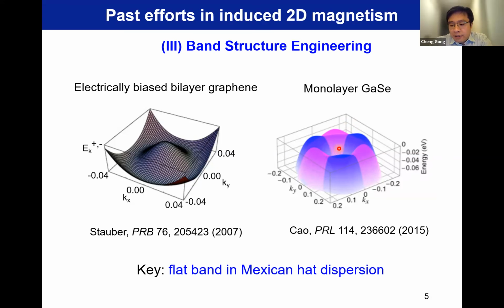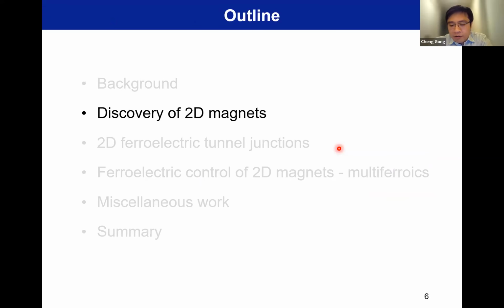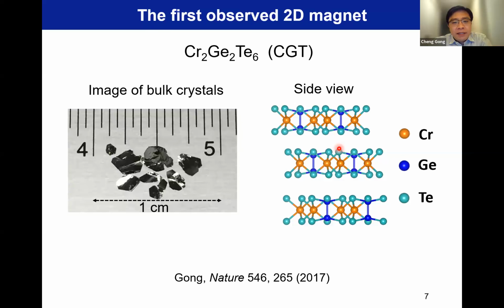What we used was a very straightforward method. Basically, there are some van der Waals materials already in nature or made by synthesis. For example, chromium germanium telluride is a bulk crystal with a layered structure, and you can exfoliate it into very thin layers. In bulk, it already has magnetic properties. It's not like a magnetic doped semiconductor, so it's not magnetic impurities, but actually part of the crystal.